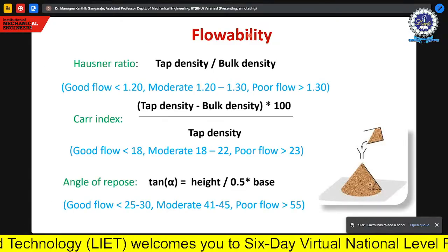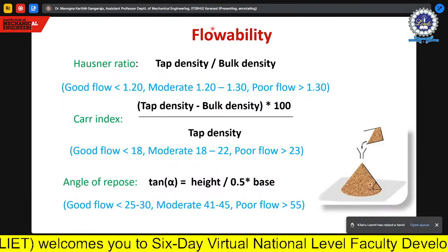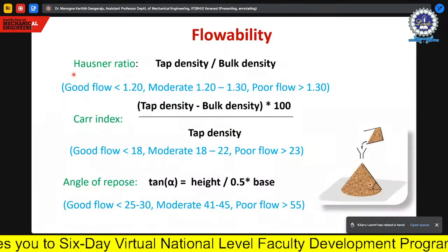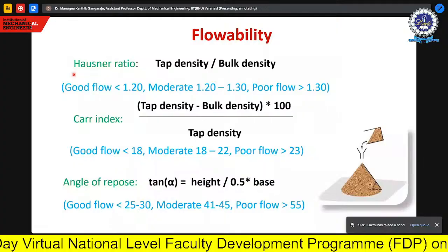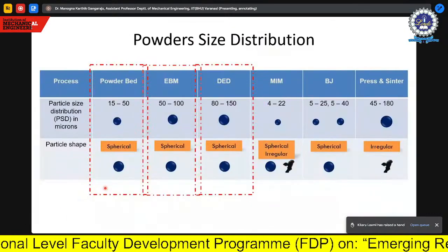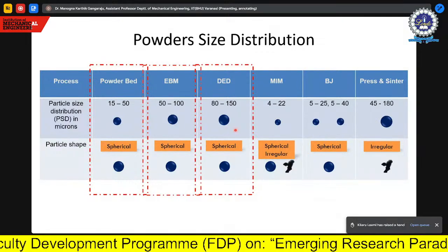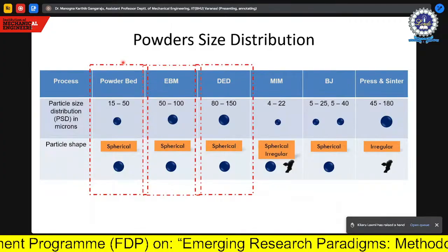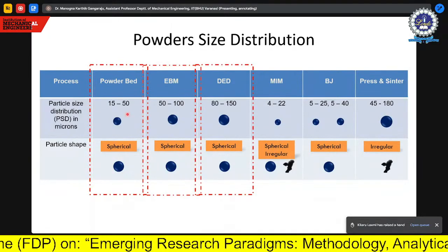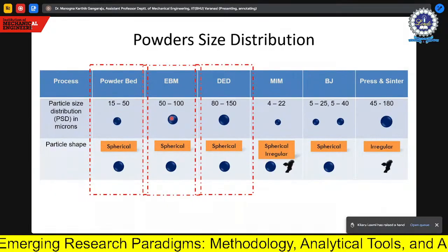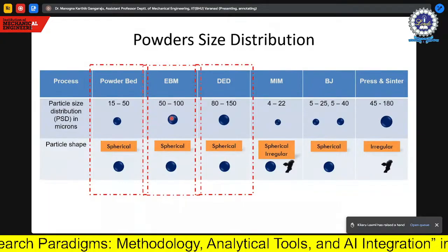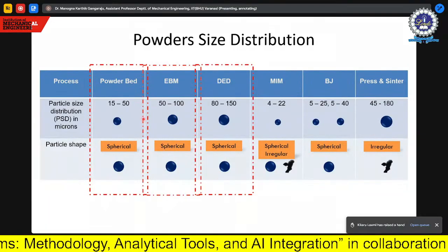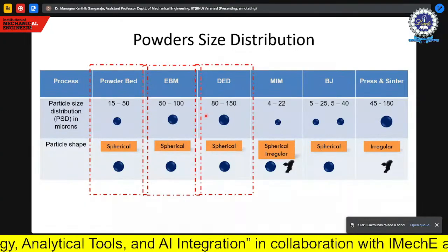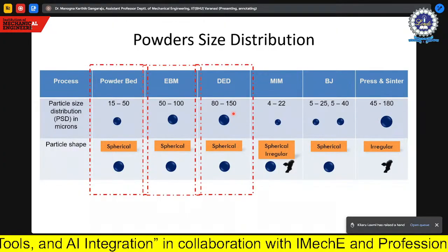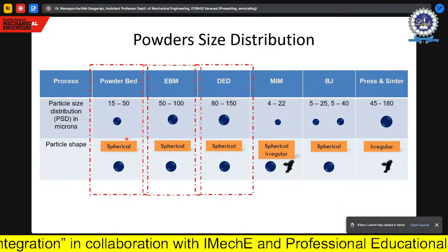This particular powder morphology will give you good flowability, because in additive manufacturing you need good flowability. There are some parameters which are given to check the flowability of the powder, called Hausner ratio, Carr index, and angle of repose. And each technology requires a particular size range of powders. So in powder bed technologies with laser, you have powders required in this particular size range. If it is electron beam, since we can use high power electron beams, you need powders in the range of 50 to 100, and in direct energy deposition you can use powders in the range of 80 to 150. So you basically require spherical powders in most additive manufacturing technologies.